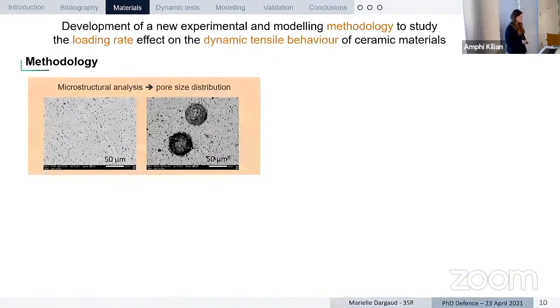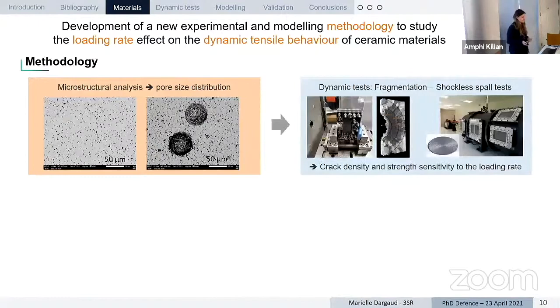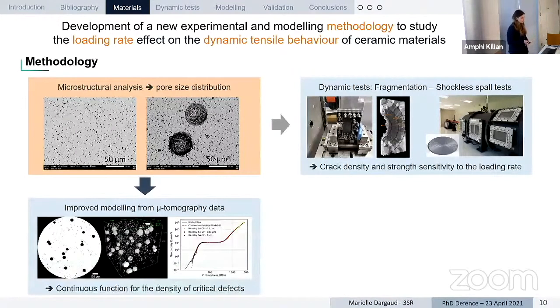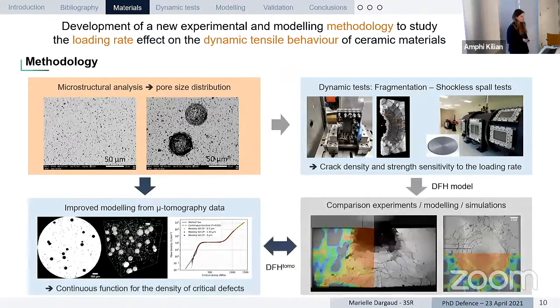So here you have the methodology to, in the end, develop a new experimental and modeling methodology to study the loading rate effects on the tensile dynamic behavior of ceramic material. First, the methodology is to start from several materials that we are going to characterize, then to perform some dynamic tests on these materials. In parallel, develop a methodology for the modeling based on X-ray tomography analysis. And by combining all of this, the idea is to see if we manage to improve the predictions of the DFH model compared to the experimental results.